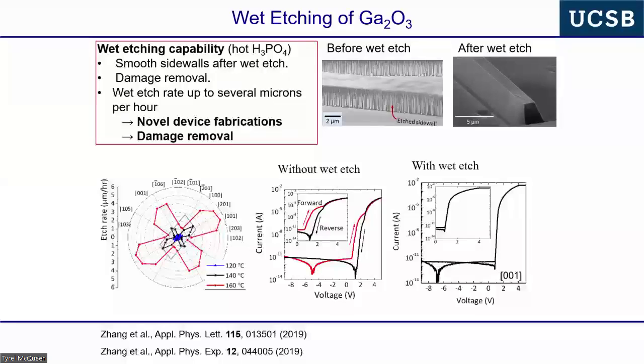The semiconductor industry lives on wet etch technology, particularly in compound semiconductors. I should make it just for those because the CHIPS Act, which is really about silicon technology, I have to make a big caveat about implantation and ion damage. Silicon as an elemental semiconductor, one can almost always completely anneal out the ion damage. In compound semiconductors, the ion damage creates interstitials and vacancies of all species. Usually one of those diffuses away too fast, and you can never recover local stoichiometry. This is why you can never fully recover ion damage in a compound semiconductor.